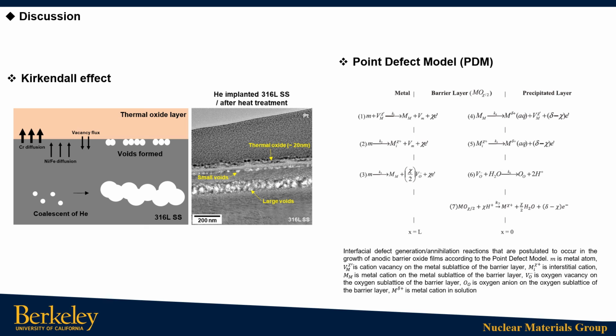The voids grow by continued vacancy condensation on the void surface, aided by the pressure of helium contained therein. Consequently, we conclude that the distribution of voids in the two regions is closely related to the generation of the oxide layer by the thermal oxidation.